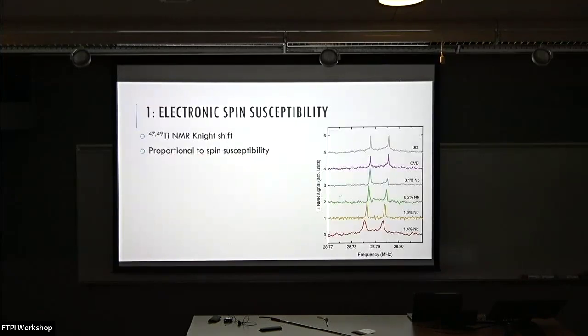Okay, so the first thing is NMR. Very briefly, this is a very simple, in principle, experiment. You just measure the titanium NMR Knight shift. So these are the spectra. There's two isotopes. They mostly do the same thing. The lines are very narrow, so this is a non-pathological system in many ways. And the lines shift a bit with doping, and they shift a bit with temperature as well.